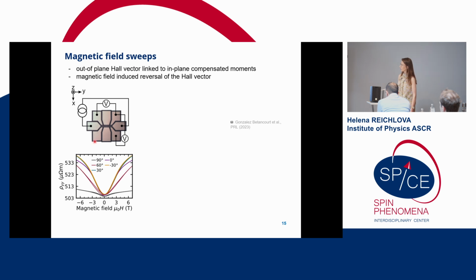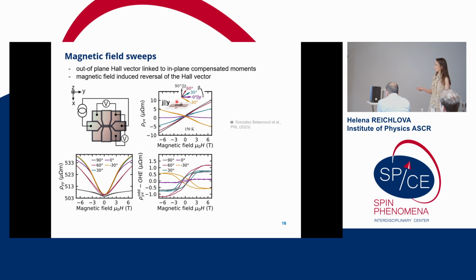And here I show just the magnetoresistance, which looks pretty conventional. But when one measures the transversal response in the Hall geometry, we can see that it's dominated by the ordinary Hall effect. This is the strong linear slope. But when the ordinary, linear part is subtracted, we can see that what is left is a clear opening, a clear hysteresis, which is present also in zero magnetic field. And you see that it depends indeed on the out-of-plane component, because it inverts or flips when we do the magnetic field sweep along 30 and minus 30 degrees. So this looks already pretty nice.